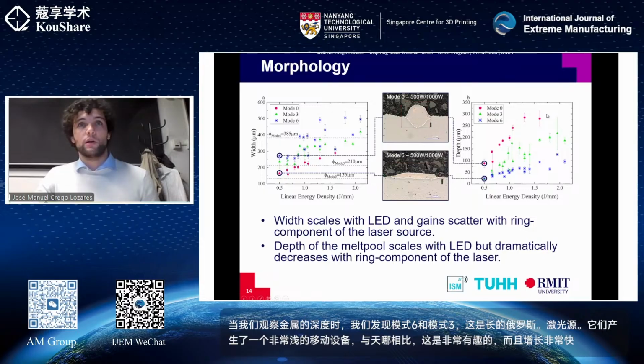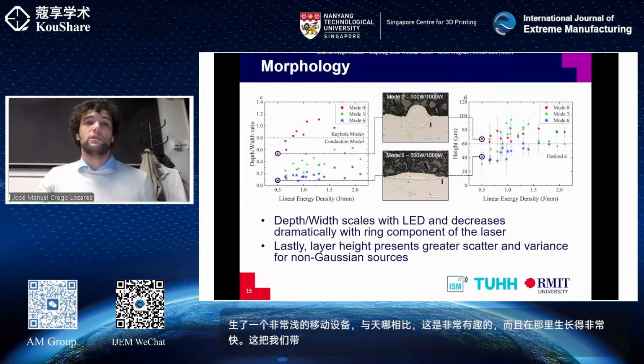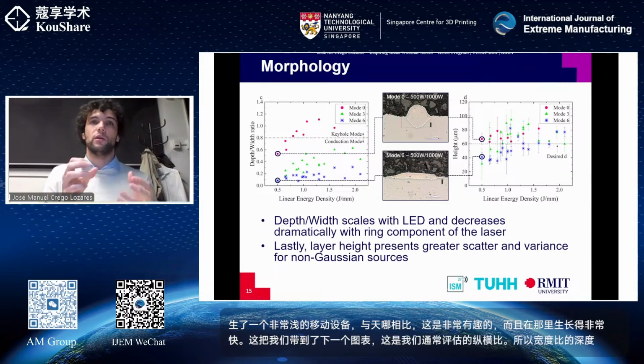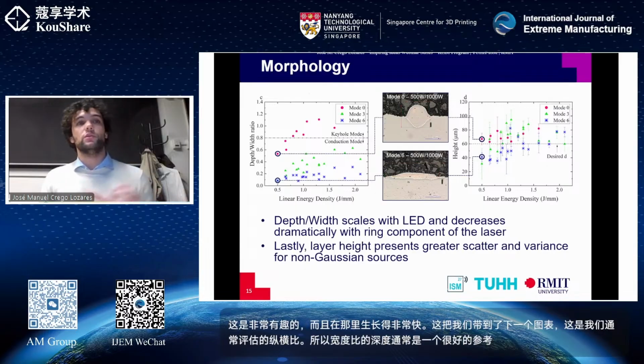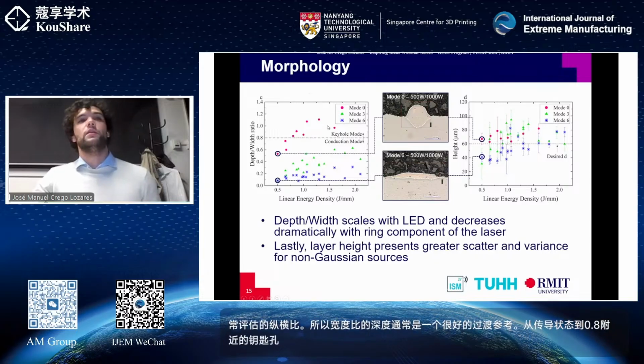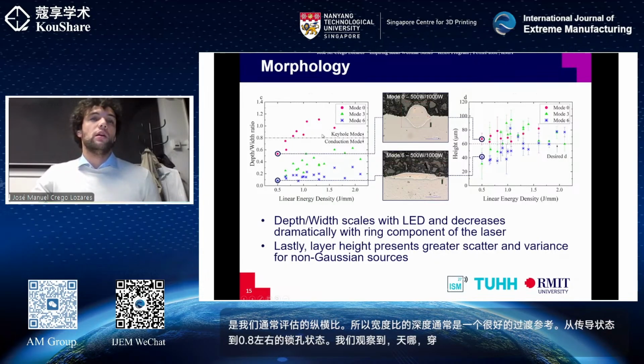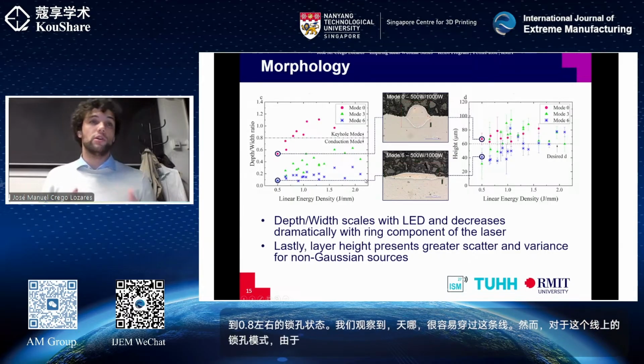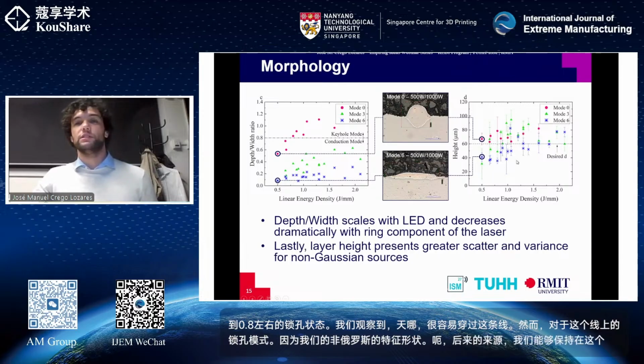Which takes us to the next graph, which is the aspect ratio that we usually evaluate. The depth-to-width ratio is usually a good reference for the transition from conduction regime to keyhole regime, around 0.8. And we observe that Gaussian crosses this line quite easily, falling above this line into keyhole mode. However, because of the signature shape of our non-Gaussian laser sources, we are able to remain under this line even at very high energy densities.